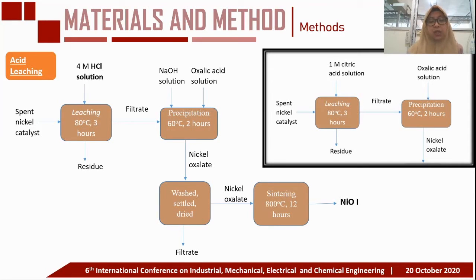To obtain nickel oxalate, the filtrate was precipitated with oxalic acid at 60 degrees Celsius under stirring for 2 hours. Precipitation results were allowed to settle, washed to neutral pH, and dried in an oven. The next step, the powder was reacted with oxygen and sintered. Furthermore, the sample was called NiO 1.